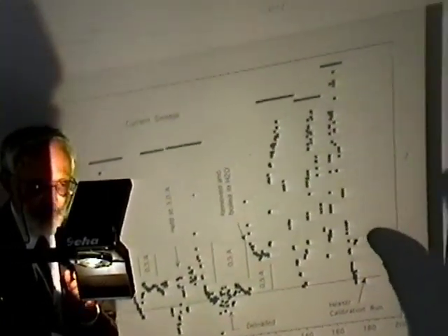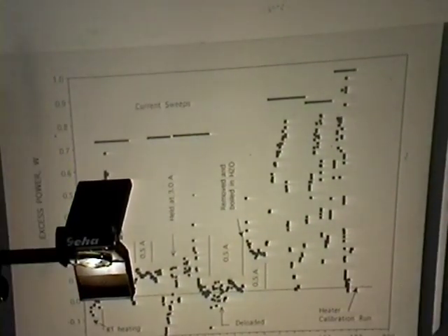Well, anyway, the people on the internet came back and suggested various explanations as to what was going on, and I attempted to answer some of those explanations. The sample was put back into the calorimeter. It showed excess power again, at half an amp. Then I went up to a higher current, and it died more quickly at the higher current. And in order to turn it back on, deloading didn't work this time. I had to take it out and boil it in water.